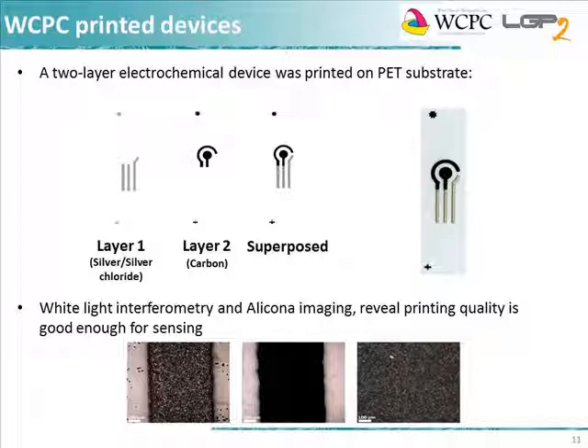Secondly, 2-layer electrochemical devices were printed in the WCPC on PET substrate, and in order to assess the quality of the screen printed electrode developed in the WCPC, several parameters were measured using white light interferometry: the width, the thicknesses, the roughness of the carbon and silver tracks, and also the roughness of the carbon working electrode. No interruption of the tracks and no hole were seen, and so the prints were concluded to be good enough